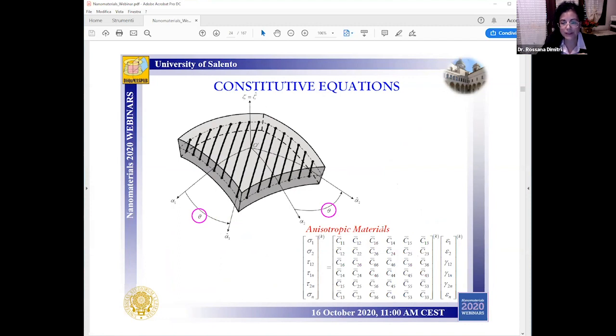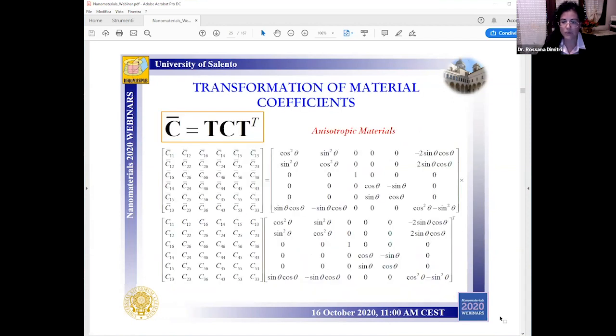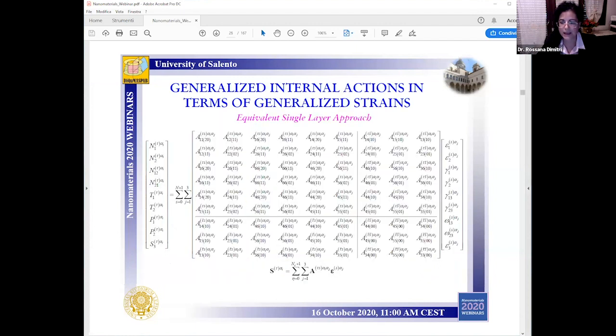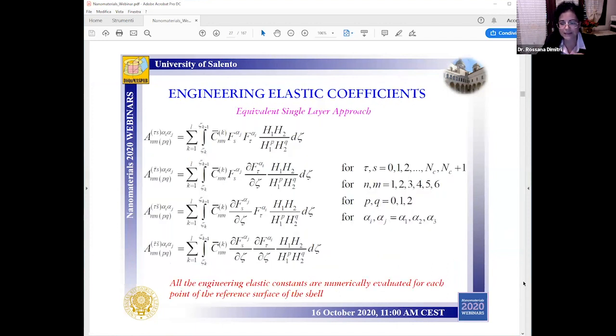here. And for each lamina made of anisotropic material, the constitutive equations in the geometric reference system can be defined as you can see here in this slide, where we determine the transformed elastic coefficients first, and then we can define the generalized internal actions reported on the shell reference surface in terms of the generalized strains by means of the constitutive operator. You can see here this block matrix, let me say, whose elastic coefficients are evaluated numerically for each point of the reference surface of the shell.